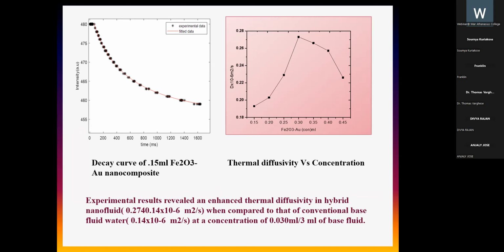It is clear that the thermal diffusivity shows an enhancement initially, which is about twofold that of the base fluid at a particular concentration in our experimental range. After that, it shows a decrease, though still better than the base fluid. The initial enhancement can be explained using Brownian motion, where the convection in liquids induced by Brownian motion of nanoparticles enhances diffusion. After a particular concentration, there is a possibility for cluster formation due to van der Waals attraction, which can reduce the molecular distance and cause a reduction in diffusivity.